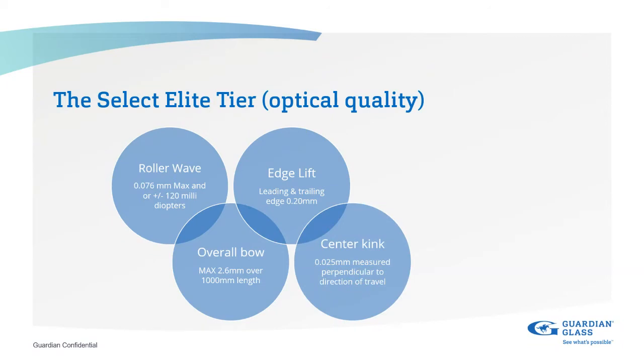Center kink, which is not basically mentioned in the standard, we've introduced. This is actually part of the program where, as the glass enters the furnace and the glass can bend, if it's colder on the top, the glass can bend and it forms like a dish inside the furnace as it rolls back and forth inside the furnace. This can cause what we call lensing effect or center kink. So part of the program also requires that we monitor and measure this as well.